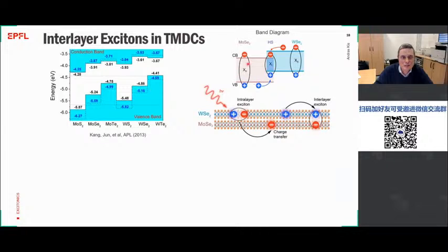And now when we shine light on a heterostructure with this kind of band alignment, what's going to happen is that you're going to create excitons in one and the other material. These will be the so-called intralayer excitons. And these intralayer excitons will be broken up inside the material because the presence of the band alignment will create a built-in electric field. So it will be like we had a certain voltage applied across the material, and this will dissociate the exciton. So it will break it up. Then the individual charges will rearrange themselves in the heterostructure. The holes will go down in energy, the electrons up, so that they minimize their energy. And what's going to happen is that you will have this very fast charge transfer where all the electrons will end up in one material, all the holes will end up in the other material.